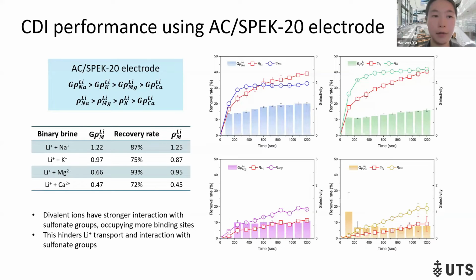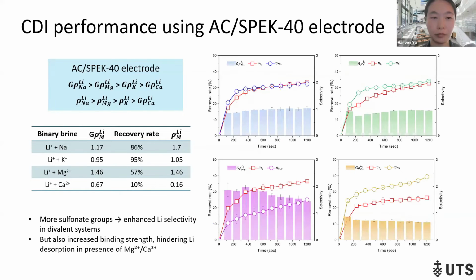Here is the CDI performance using AC/SPEK-20 electrode. We found the divalent ions have stronger interaction with the sulfonate groups, occupying more binding sites, and this hinders lithium transport and interaction with the sulfonate group. And with the AC/SPEK-40 electrode, we found more sulfonated groups can enhance lithium selectivity in divalent systems, but also increase the binding strength, which hinders the lithium desorption in the presence of the divalent ions.